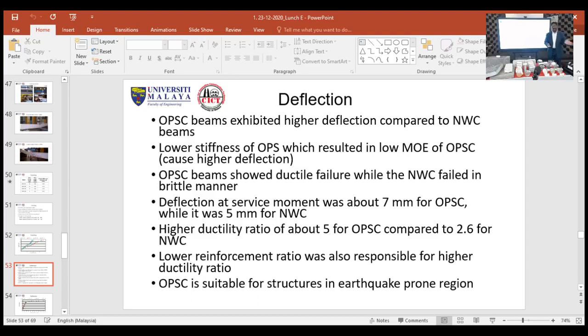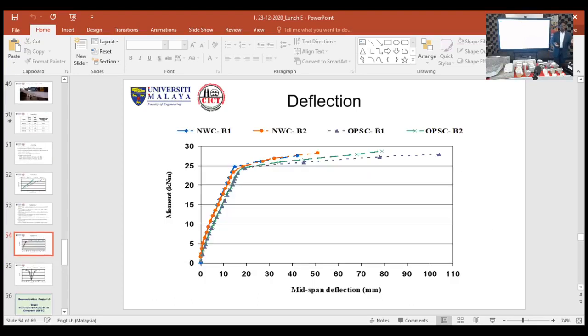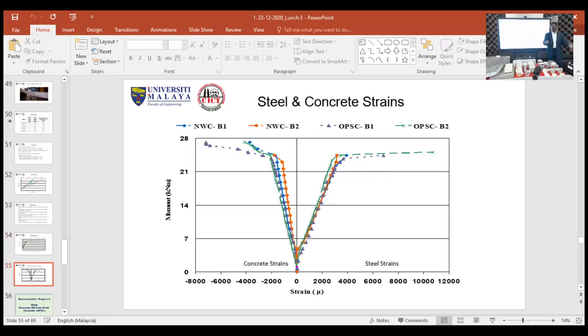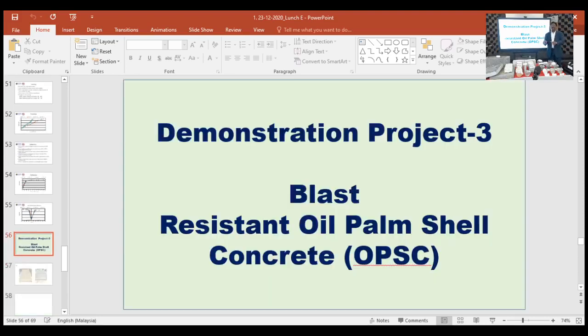And this is the deformation. We can see that the deflection for the normal weight concrete beam is around 40 to 50 mm, but for the lightweight concrete, the deflection was about 100 mm. And the strain characteristics also, we compared the strains of both normal weight and lightweight concrete. Because of the bond and because of this deformation, the strain was much higher compared to the normal weight concrete. This led us to the next stage as a pinnacle of our research on this oil palm shell.